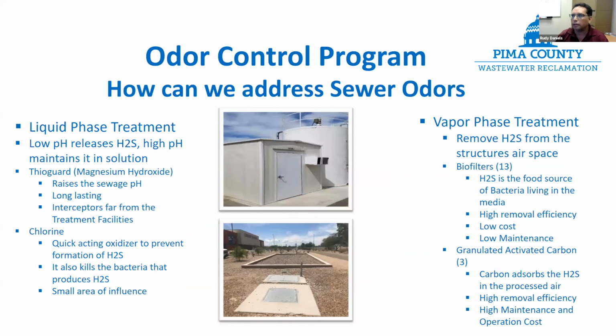And so how do we address sewer odors? Well, within our department, we have a liquid phase and a vapor phase. Within the liquid phase, we are using magnesium hydroxide, also known as Thiogard, that is very long lasting. It's very potent in reducing H2S levels within our large line interceptors very far from our treatment facilities. We also are using chlorine, which is good for short areas of concern, but the area of influence is very small and it is not as effective on our conveyance systems in comparison with